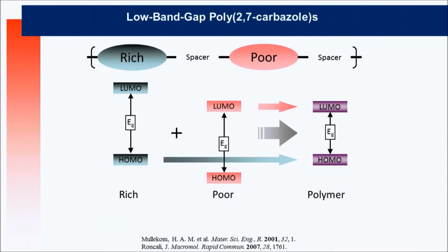And what we like with this approach, it's called an alternating copolymer. If you copolymerize carbazole, which is an electron-rich unit, with an electron-poor unit, you can get a different band gap, and that will reduce the band gap also. So quickly, in the alternating copolymer, the HOMO level is more or less driven by the HOMO level of the electron-rich unit, and the LUMO level of the resulting polymer here is driven or pinned by the LUMO level of the electron-poor unit, and therefore you can tune the band gap and reduce the band gap, and that's very important.